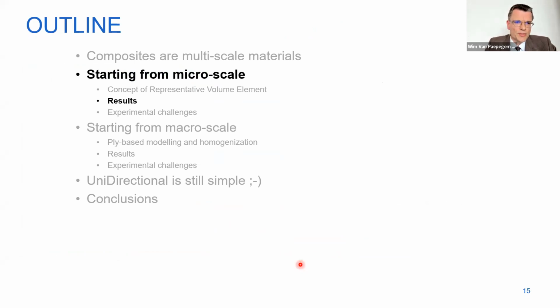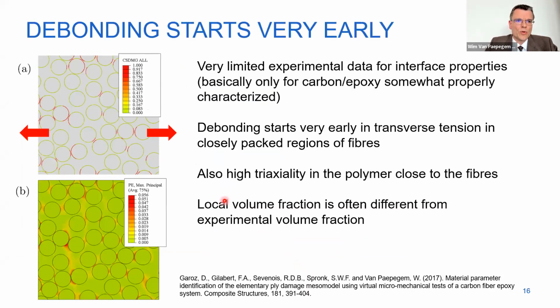And then some results. First of all, if you apply transverse tension, indeed you typically see debonding at an early stage. So this shows the damage of the interface. And also the maximum principal strain in the matrix is quite high. So you have indeed also a high stress concentration in the polymer.